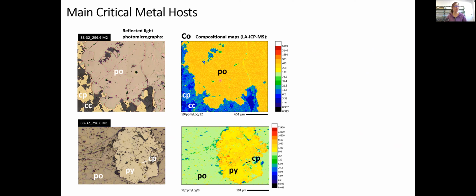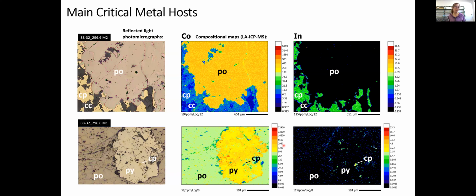So, okay, that's important. If we look at this map, though, we see that pyrite hosts even more, in this case, several thousand ppm. So this is why I say warm colors will always be higher, but the actual numbers might change. If we look at another critical metal, indium, well, almost all the indium in these samples is in the chalcopyrite here or in these little inclusions over here. And I can do this for all the critical metals we're interested in, just to get an idea of broadly where they're sitting.